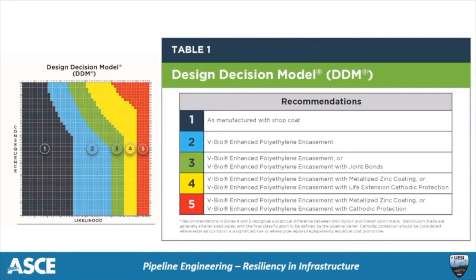The model balances the likelihood of corrosion against its consequences and provides a recommendation for corrosion control. The recommendations range from relying on ductile's inherent corrosion resistance in zone 1 to the use of V-Bio enhanced polyethylene encasement in zone 2 to the use of a metallized zinc coating and V-Bio enhanced polyethylene for distribution piping systems in Zone 5. All of these recommendations have a benchmark goal of providing a minimum average service life of 100 years.